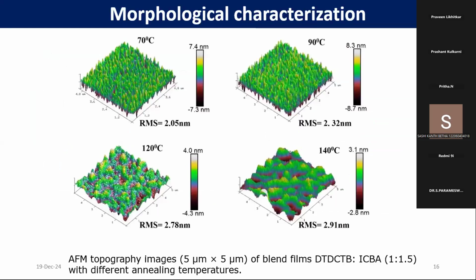So that is another thing, and we need to study the structural characterizations also, like how the blend films are formed, what is the RMS value, and how well both donor and acceptors are mixed together, so that they are able to form the bicontinuous networks. So at 90 degrees Celsius, it is giving 2.32 nanometers, and it is able to form fine structure with the bicontinuous networks. This is the morphological characterization of blend films.